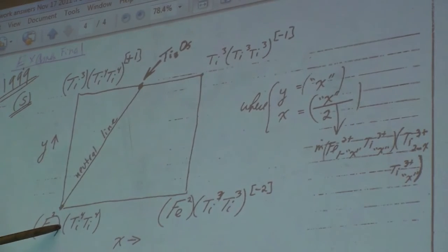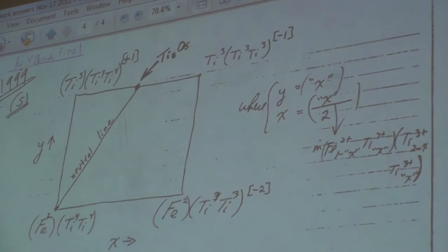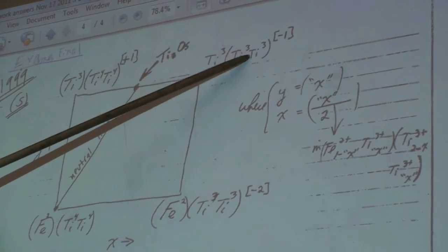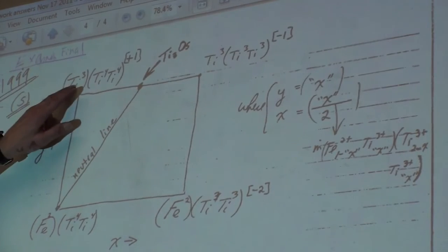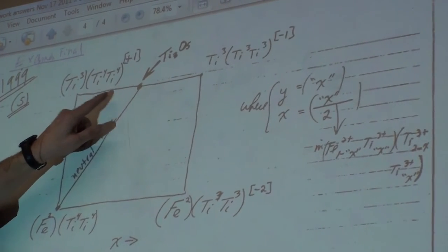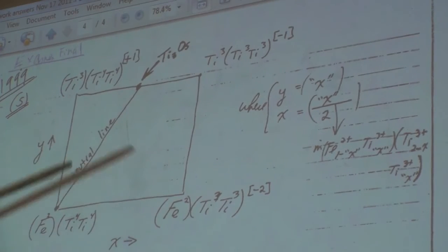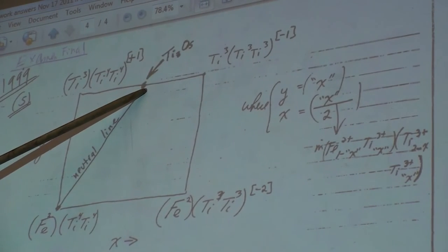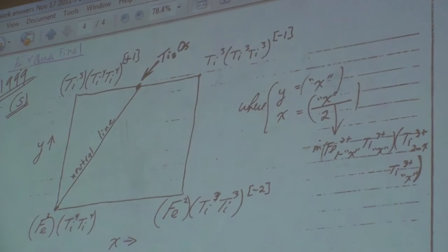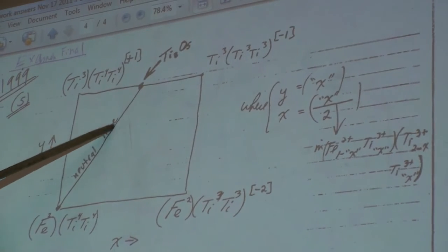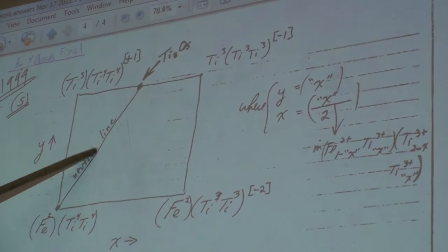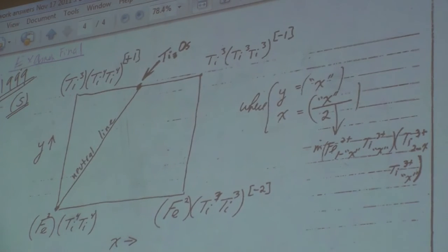This is your neutral line, and at the end of this neutral line is Ti3O5, which has titanium 3+ here and a mixture of titanium 4+ and titanium 3+. So it's halfway in between. And that's your neutral line, which is your real binary system between ferro pseudobrookite and Ti3O5. All real solutions necessarily lie on this line because that's the only neutral line. But where on this line? Well, it depends on the overall composition.